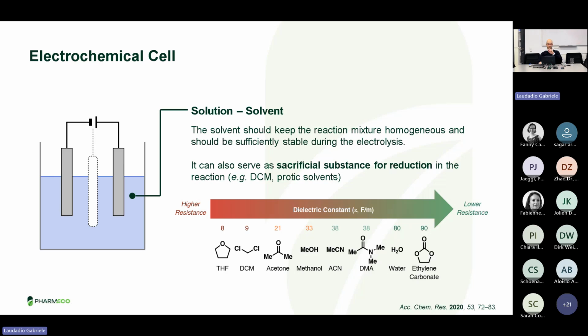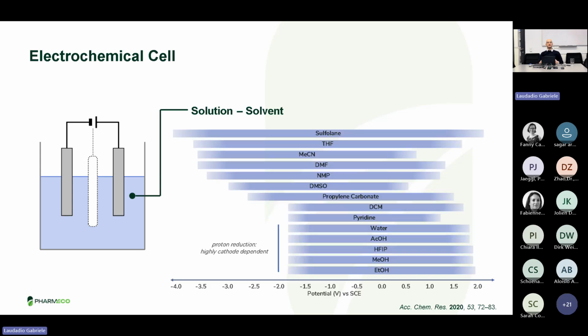Another thing that is very important to take into account when we choose the appropriate solvent is the redox potential window. It's easy to understand that every solvent will have a potential where it starts degrading, from a reductive or an oxidative point of view. So we have to choose a solvent that can operate within the redox potential that we would like to exploit. For example, DMF is very good at most of the redox potentials that are commonly used, while acetic acid or water have limited application in terms of reductive potential.